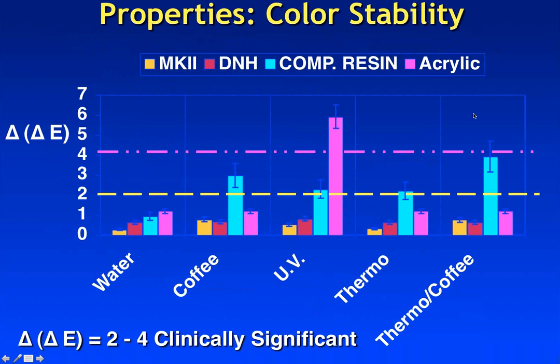We look at color stability, which is another issue with composite resins. The yellow is Mark II. This weird reddish color is the Enamic DNH double network hybrid. You then have a composite resin in this kind of aqua color, and then temporary bridge resin in this bizarre pinkish color. Things look very strange on my screen. Now, most people can see a color difference when you get to a delta E of between 2 and 4. If you can't see it when you get to 4, then you better have someone else taking your shades for you because you're in trouble.